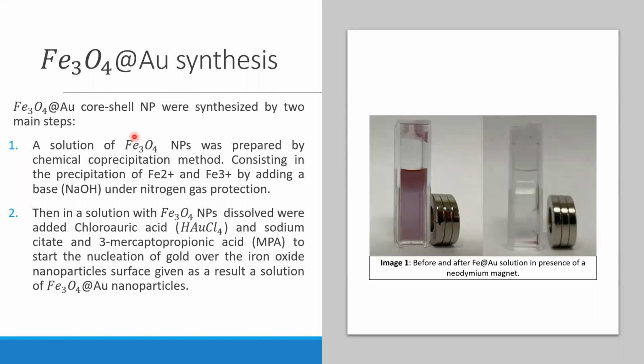Now let's jump into the paper. The paper starts with the methodology of this paper, but this starts with the synthesis of core shells. The core shells in this paper were synthesized by two main steps. The first step is generating the iron oxide nanoparticles. This was prepared by the chemical co-precipitation method.